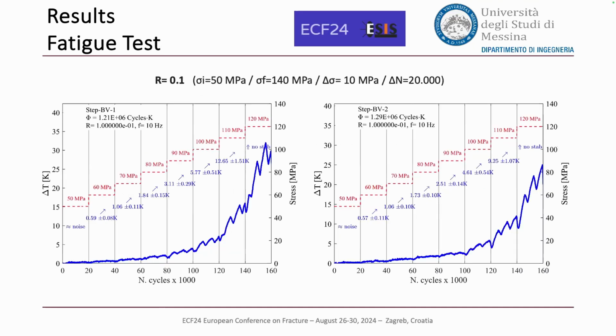So we move on to the fatigue test, the stepwise fatigue test. We use a load ratio of 0.1. The initial stress is 50 megapascal and the final stress is 140 megapascal. The delta for each step is 10 megapascal, and each step lasts 20,000 cycles.